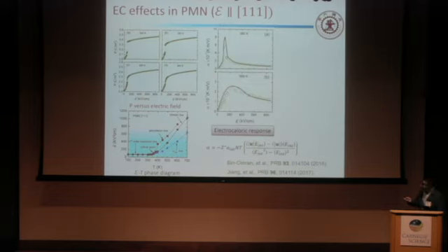Then we calculate the electrocaloric effect coefficient for different temperatures. Why do we choose these two temperatures? Because this temperature is near the critical point. We also show that the critical point is about 360 Kelvin. So we choose this temperature near the critical point, and this temperature far away from the critical point.